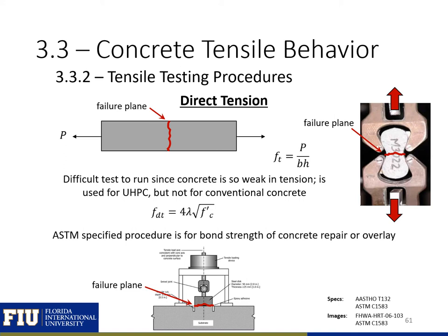This type of test is also used to determine the bond strength between two materials or at a cold joint. Details for this test can be found in ASTM C1583. This test pulls on a steel piece embedded in concrete, as shown in the figure on the bottom of the slide, and tests the tensile strength of the interface plane. If the bond strength of the interface plane is greater than the tensile strength of the substrate, then the failure plane will be located in the substrate.